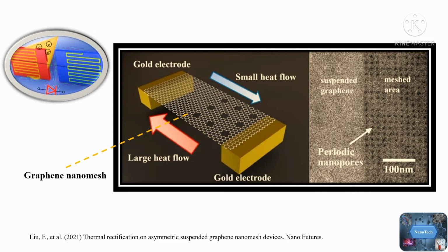So, these research findings have shown that the thermal rectification phenomenon can be observed at low temperatures with a high ratio of up to 60% on suspended asymmetric graphene nanomesh devices, at 150K and 250K. They use graphene nanomesh as an artificial phononic crystal structure on half of the heat flux channel's area.